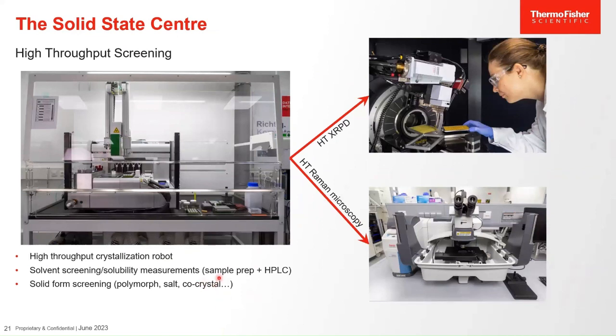So our high throughput screening is carried out in a crystallization robot, which you see here on the right-hand side of the screen. This allows us to dose solids and liquids, our solvents, automatically. We can prepare solubility measurements on this machine. The solubility is actually measured via HPLC. And we can carry out our crystallization experiments. And once we've carried out the crystallization experiments, as I mentioned, we use XRPD, top right here, for initial characterization, and Raman spectroscopy for spectroscopic characterization. Both of these are high throughput instruments, highly automated, and we can just run through all the successful experiments without great manual intervention.